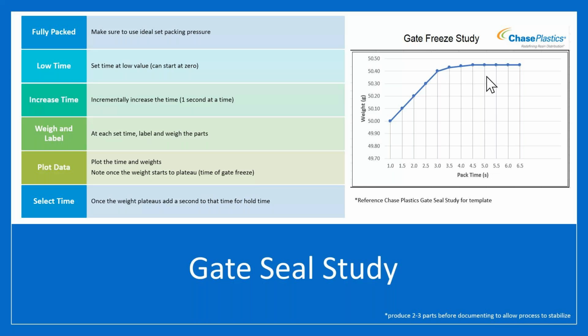Oh, gotcha. So now you're looking at part weight, flash, voids, and sinks. As soon as you have a part that is acceptable weight and acceptable quality, you can close the gates down. And then the valve pin itself is going to prevent the backflow. Okay. So it does have its challenges to apply a decoupled two process, but family molds are one of the more difficult just because of the dissimilarity in volumes. And you can play games with balancing runners and choking things down, speeding things up, but do know that having those different runner sizes is going to change the amount of shear heating in each of those legs of the runner, which will still result in slightly different molded in properties.